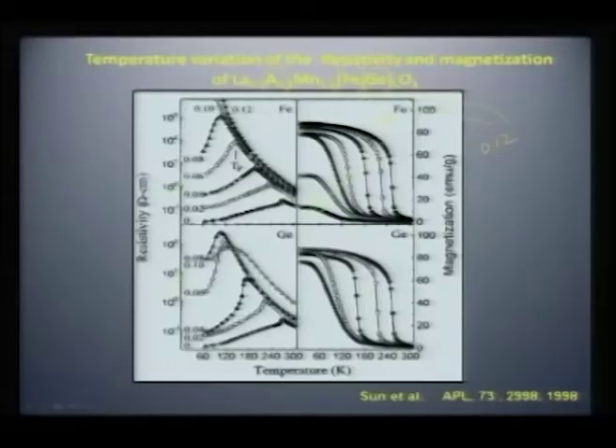Practically it goes very weakly ferromagnetic, and the same situation is there when you look at the resistivity versus temperature function. As you increase the iron concentration to 12%, it completely transforms into an insulator. Same situation for germanium. As you substitute, you see the Tc decreasing, and as you substitute germanium, you see the resistance going almost to an insulating stage.